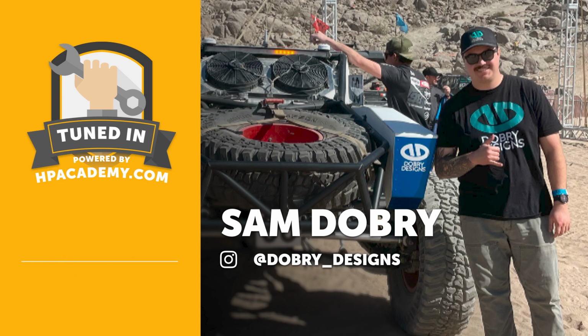Yeah. So in real easy terms, you're talking about essentially taking your whole finished weldment and baking it, putting it in a furnace, and getting it hot enough for a long enough period of time. And it all depends on the material that you're trying to work with, to where it fully anneals the whole part. And so that stress relieves the entire part. It's all super soft. Any of the tension that's built up from the grain dislocation from the hardness when you're welding is all relieved.